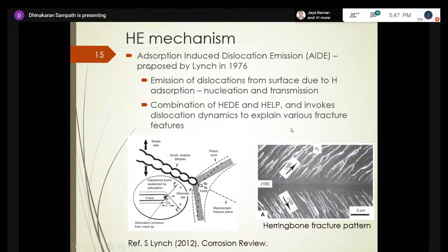Because there are several, but for this presentation I've taken the most important three. Adsorption induced dislocation emission. Once the hydrogen enters the surface, it creates a dislocation and helps to move the dislocation, which means we get this localized shearing. And at the intersection, it forms voids that lead to cracking, continuous cracking. So this is adsorption induced dislocation emission, as the name says. And it explains this herringbone fracture pattern very much because it shows this crystallographic pattern.